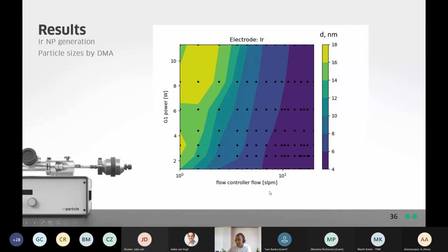On the x-axis, we have the gas flow rate. So this goes from 1 liter per minute to about 15. And on the y-axis, we have the total power output. And what you can see is that we've got several different data points, which shows you that we can vary and tune the particle size between 4 and 18 nanometers just by varying the gas flow and the power output. So this also then helps the end user to quickly get going with preparing these materials.